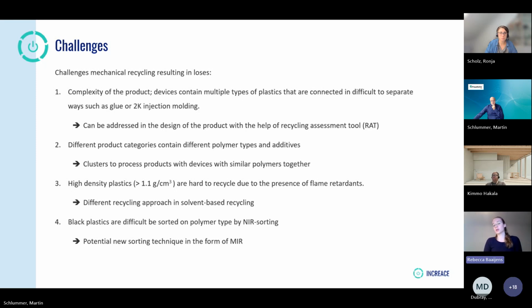And then for us, specifically high density plastics, that's why we have the cutoff point at 1.1 grams per cubic centimeter. It's because they're typically very hard, as Martin already said, with regards to hazardous materials that are being used. So often that's brominated flame retardants. And then we're also currently by legislation required to make sure those are incinerated at such a temperature that those flame retardants are destroyed. So one of the avenues there is to go towards solvent-based recycling, which we will talk about more.